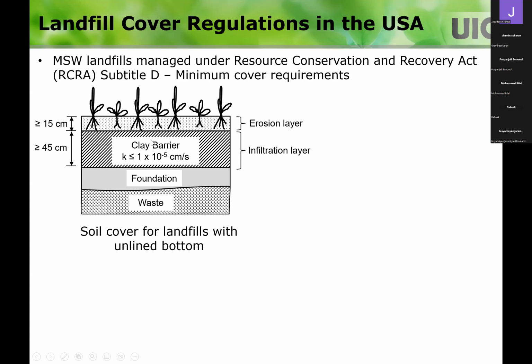And the thickness has to be greater than or equal to 45 centimeters. And then on the top, 15 centimeters of erosion layer. So this is important because I told you that you need to have a geomembrane on the top, but you don't have to have a geomembrane if the bottom is unlined. If the bottom has the composite liner, you have to have a composite liner on the top. But if you don't have a composite liner at the bottom, you can have just soil layers.